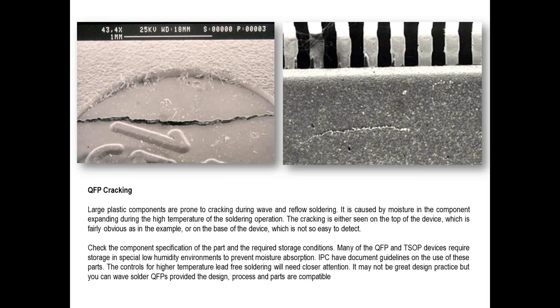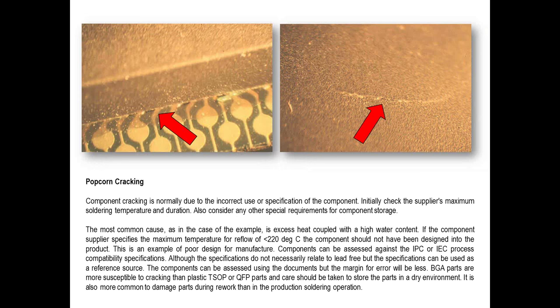To avoid doing second stage assembly, which is something which should be avoided wherever possible, because it obviously has a major impact on the cost of building a product. And subcontractors don't like it also. Here's an example of cracking of BGAs. And here you can see I've pointed out with a couple of red arrows where moisture has expanded and actually escaped through the package, causing a crack line at the interface between the plastic and the fiberglass, or in the second example on the right-hand side, right through the plastic.